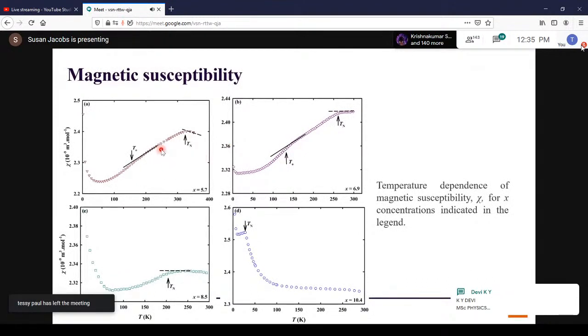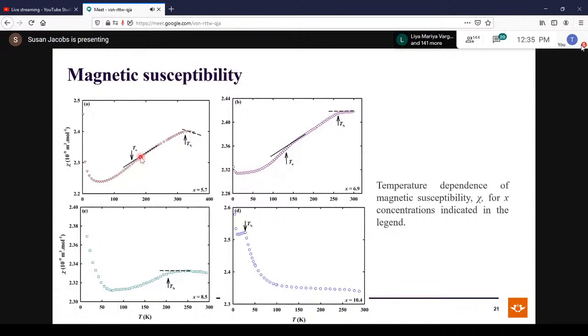So then we thought, okay, that means this second change of slope, which is similar to the antiferromagnetic transition, should then correspond to the oxide transition. And chromium oxide, Cr2O3, is antiferromagnetic. So we concluded that this then corresponds to the oxide transition.